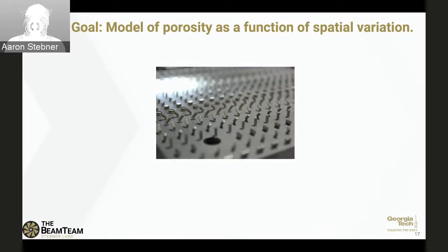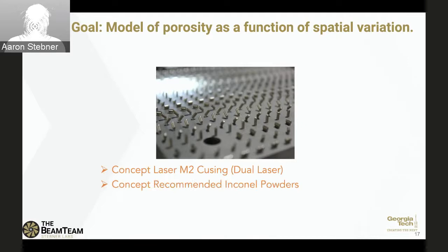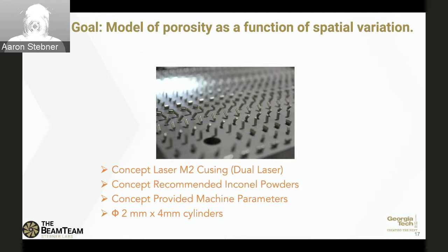And so then what about our goal of modeling porosity as a function of spatial variation? So we build up plates of these cylinders. We built multiple plates. Go ahead and click like three times, I think. Just get these on here. So we used one printer. We used the manufacturer provided material. We used their parameter set, and I think once more. And yeah, made the same geometry, and all we varied was where they were and how they were oriented on the plate. And then we built multiples to test our similarity hypothesis. Go ahead and go to the next slide.